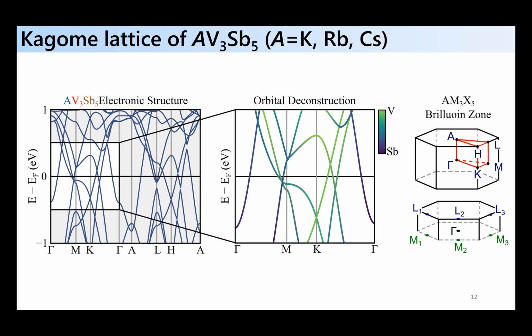Okay, and also if you're looking for kagome-like features at the K point here, you can see there's a Dirac cone. So you can start to see that there are some elements of even these simple tight-binding type predictions of kagome band structures manifest in the system, and some of the more interesting features are rather close to the Fermi level.